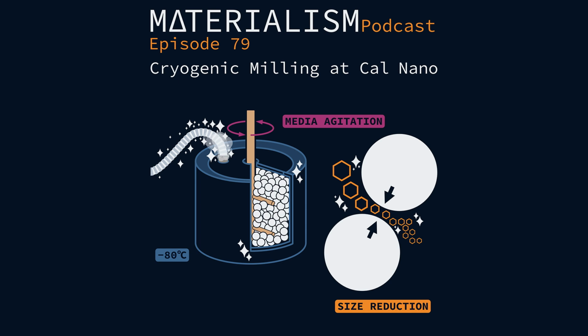Yeah, you definitely can see some benefits if you want to spheroidize it for flowability, but it's really a test of a specific material. So if you're having a material that particularly flows really bad once you get it down to that nanoparticle size, then using a process like that is going to be needed. But a lot of times, as long as it can get into a die... If it's not broken, don't fix it. Don't add a step if you don't need to, right? So that's exactly what we do.